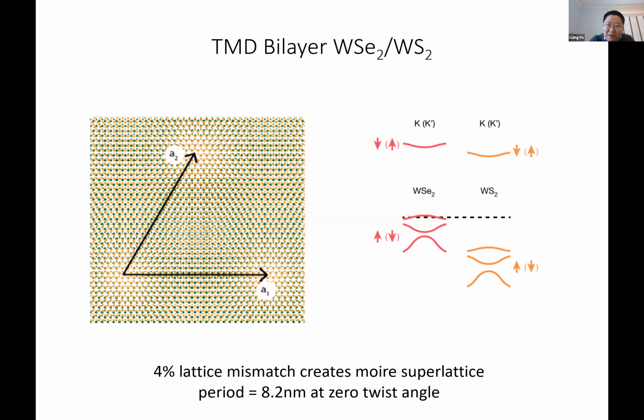So these are experimental groups. They measure the second harmonic generation on the WSe2 layer and on the WS2 layer separately. And by looking at the polarization dependence of the second harmonic generation signal, they can infer the alignment of the angles. And it turned out that the alignment is essentially a zero twist angle, within some uncertainty of less than 1 degree. And that gives you an idea of the Moiré area. So you know the Moiré area and you know the charge density, and you can convert it into the filling. Yeah.